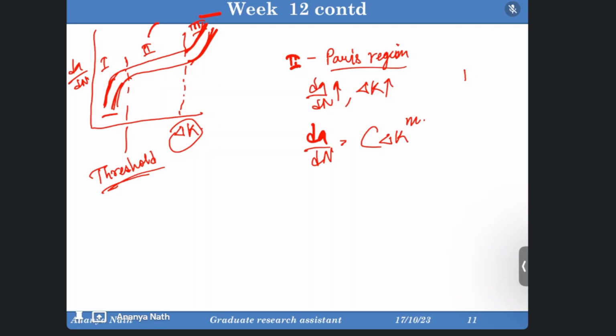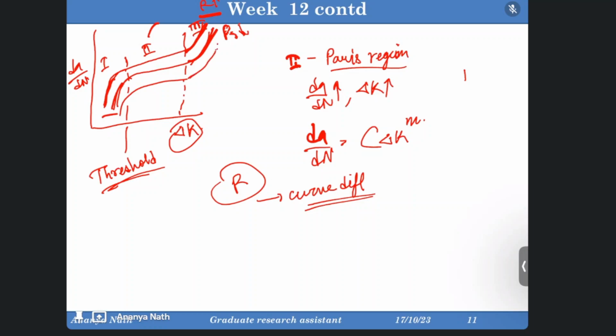So the Paris region equation is denoted with this. It's more like a power law again. M is the Paris law exponent, del K is the stress intensity factor range, and C is the proportional constant. Depending upon the M value, things will be different, and depending upon the stress ratio as well. For different stress ratios R, the curve will be different. It's not that if you increase the R value, the curve will always go in the upward direction. It may happen that with increasing R value, due to different values of minimum and maximum stress, the curve may get lower.